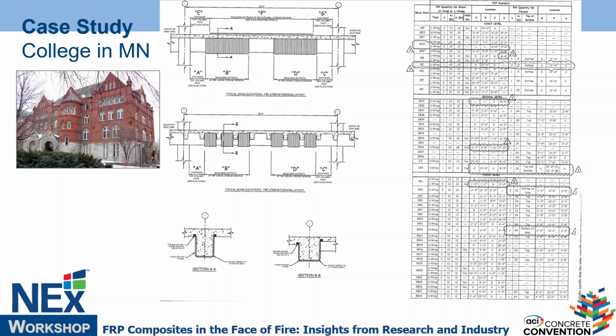We said, okay, this is the approach, here's the evidence. We are going to run through this calculation, show you one by one, capacity versus demand after 2 hours. If it passes, we don't need fireproofing. If it fails, we'll apply fireproofing. And sure enough, by running the calculation, we found only 30% of all the elements require fireproofing. Okay? So it wasn't required for all of them, right?